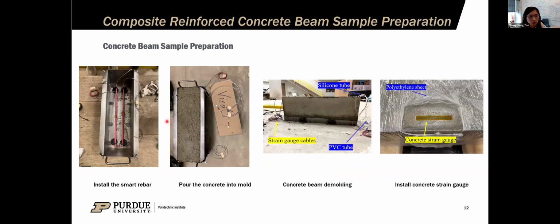And we have some extra protection for the sensor cables at the edge area of the beam using the PVC tubes. After several days curing, we can demold the concrete beam. And in order to monitor the strain of the concrete, we also install another 2 concrete strain gauges at the bottom area and the front area to collect the strain data from the concrete.